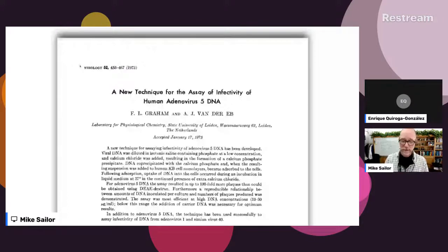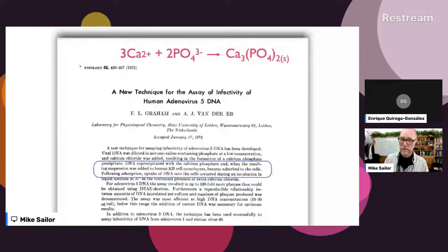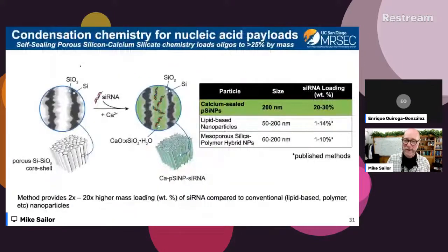And so then we went back in the literature and looked at how people have stabilized nucleic acids and how the body and living systems stabilize nucleic acids. And it turns out it's well known in that community that you can precipitate DNA by adding calcium ion. In this case, it was calcium phosphate or calcium chloride, because calcium phosphate also makes a very insoluble compound, very similar to the calcium silicate that we were talking about a few minutes ago.